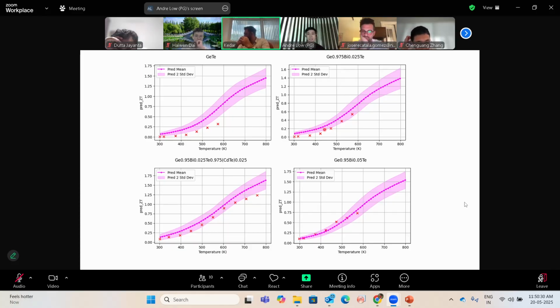You're not actually predicting the whole curve, the ZT. You're plotting point by point still, and then replotting it like this. Is that right? So when it comes to the inference, what Paul did was he just took every 10 degrees, 10 degrees, 10 degrees. I mean, it's arbitrary, right? You don't have to do such a small temperature step. You just need enough data points to form a curve. So we kept ourselves to 300 to 800 Kelvin because that seems to be roughly the interesting range.